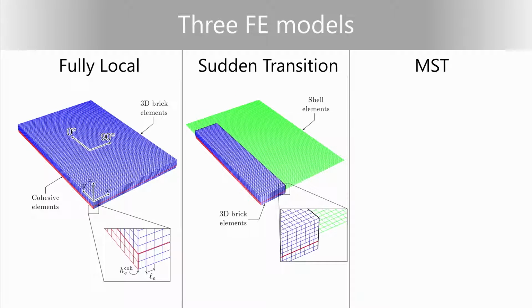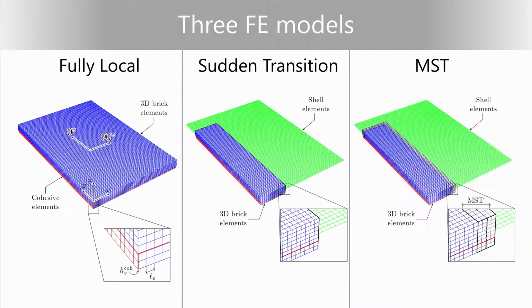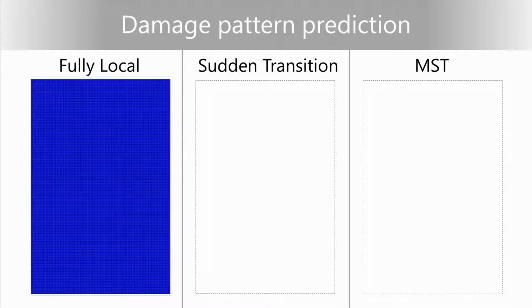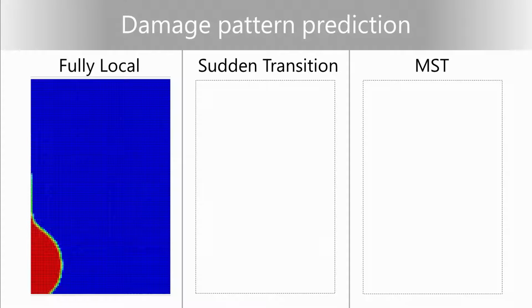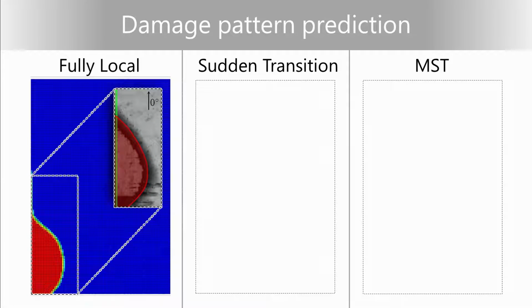We've done one model in which we have a sudden transition between part of the model in 3D and part of the model with shell elements. And we've done a third model with our mesh superposition technique. So if I show you first the results with the fully local model, this is the delamination growing. You can see it's getting that peanut shape. And if you compare that against the experiments I had shown you before, you can see that they match pretty well. So it's a good detailed numerical model.